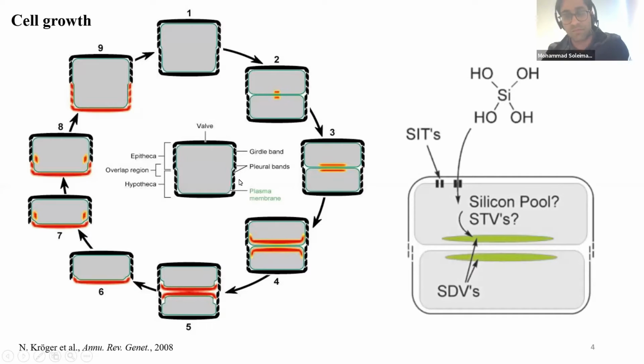The way the diatom makes this silica structure in biosilicification is that they take up orthosilicic acid from the environment, which is a soluble form of silica, and with a specific protein known as silicic acid transporter protein, they transport this silicic acid from the environment to the inside of the cell. There is a lipid layer around the silica structure, and this protein helps the organism to take up silicic acid, which is the main ingredient for building the silica structure.